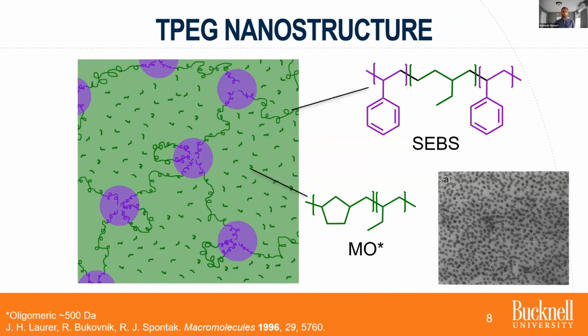And so here's just some basic information about thermoplastic elastomer gel nanostructure. The big things here are, this is the micrograph from before, from Rich's first work, one of his first works in thermoplastic elastomer gels. And then the schematic on the left is kind of what we envision the nanostructure as looking like. Some of these features are difficult to ascertain as far as microscopy or scattering goes, and simulation really helps us to understand those things. And so our gels are composed of styrene, ethylene, butylene, styrene, triblock copolymers, as shown on the top right here, and then an aliphatic mineral oil. This is kind of a generic structure. This isn't the specific structure of the mineral oil we use, but this is, again, a general capture of what we think it kind of looks like.